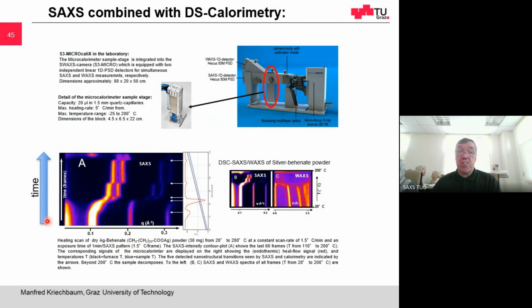So here's such an example. This is a contour plot, time here. There are maybe 100 frames. Here's angle 0. So here's this scattering pattern in the contour plot. So you see the nanostructural changes. And here you see the thermal signal. So we have a transition here, and here. So at the same time, you measure heat signal and nanostructural changes.